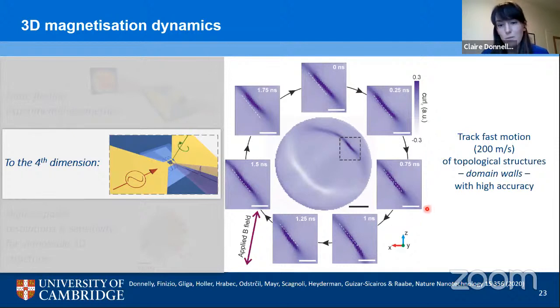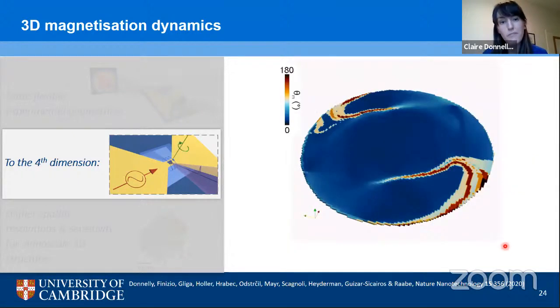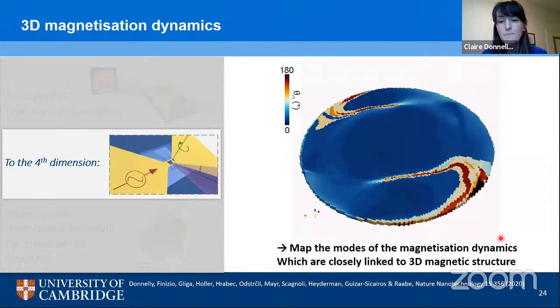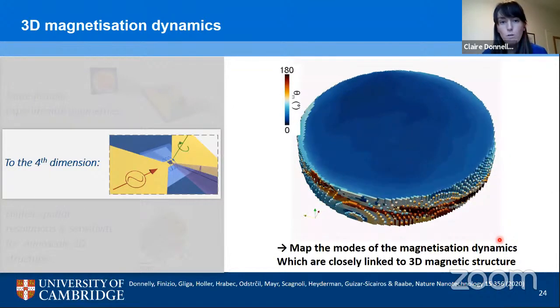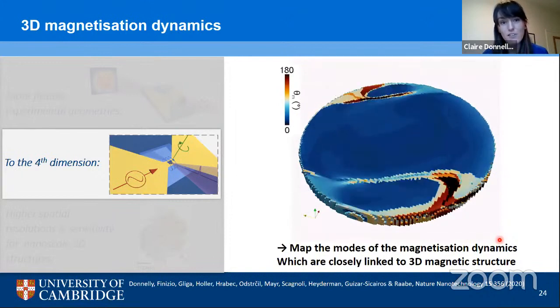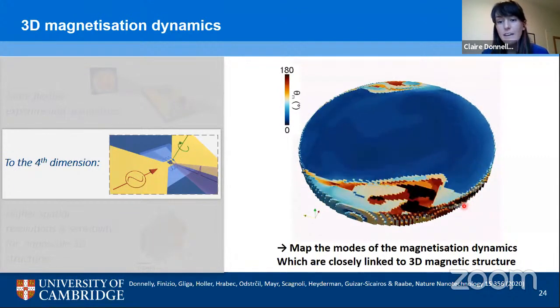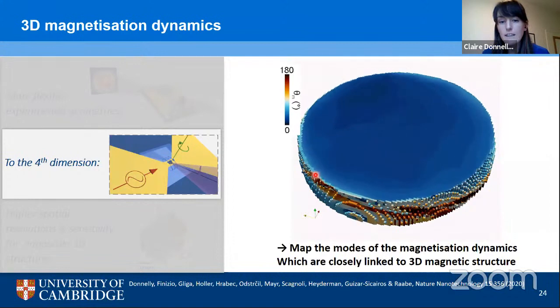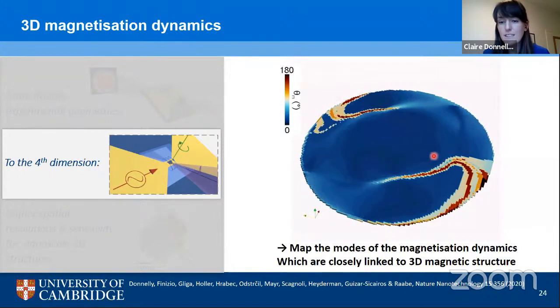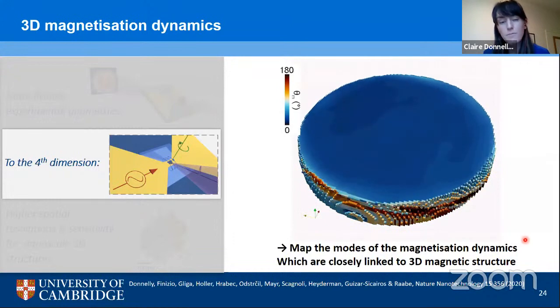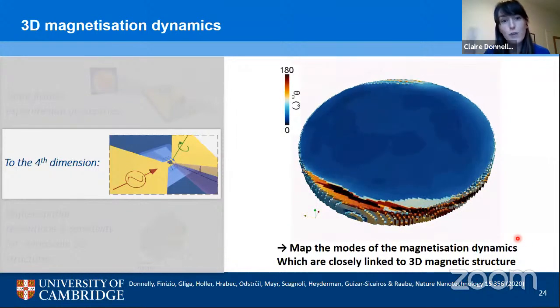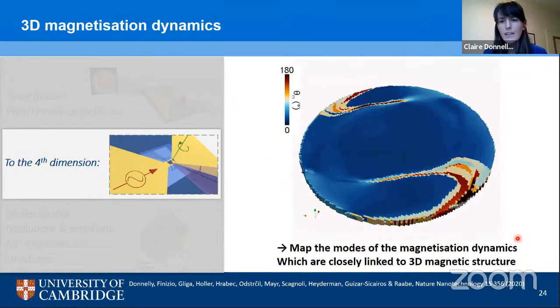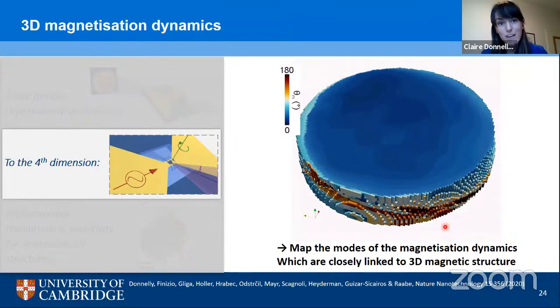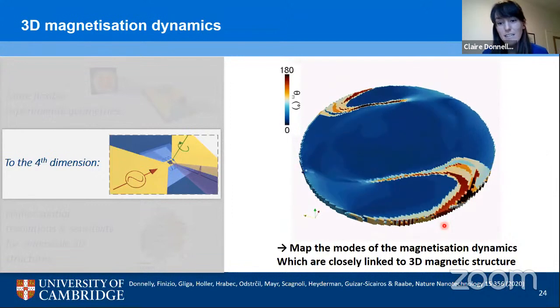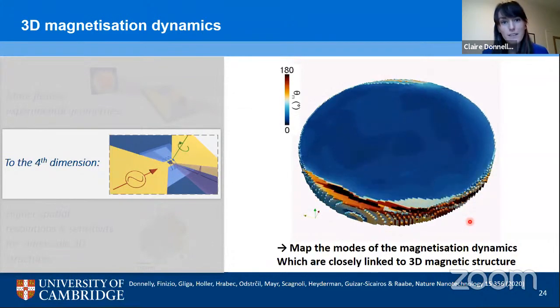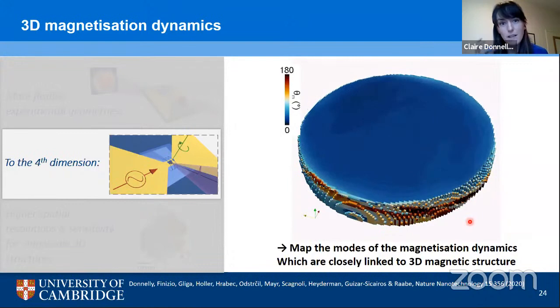But that's not all we can do with this new technique. We can also perform Fourier analysis of our four-dimensional data and therefore identify modes of coherent rotation of the magnetization within the bulk of our structure. And here, what we're showing you is such modes. So the red structures in this 3D image correspond to regions where the magnetization is precessing at a high amplitude. Now we see that the magnetization precession seems to be very closely related to the 3D magnetic structure, again providing more insight into the dynamics of these bulk 3D systems.